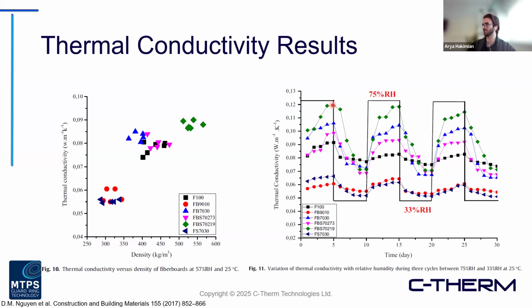This one here, I'm not going to read the code. The one in green, you can see at a high relative humidity, this was based on conductivity, had the highest value. But when we drop down to a lower humidity, it actually has an even lower value than, let's say, the black one or the blue one here. So it used to be the highest conductivity material under one condition, but it was on the lower end under the other. So understanding which materials you're going to select is very important, to see how they respond to these different environmental conditions.